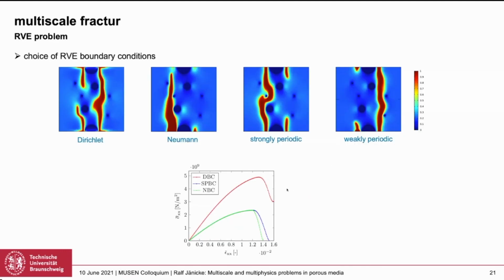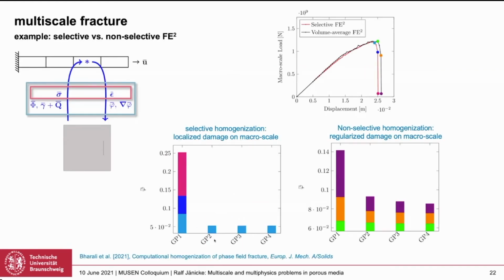So, this can be used for RVE studies with various types of boundary conditions. Because I'm talking too much, maybe I can keep that short here, and then we see that the more restrictive the choice of boundary conditions, the more stiff the behavior in these stress-strain curves will be. Maybe that's just a side aspect. And now we were interested in the two-scale behavior, and since this is really expensive, we ended up really with a Mickey Mouse problem here, but it was to illustrate how it works and that it works at all.